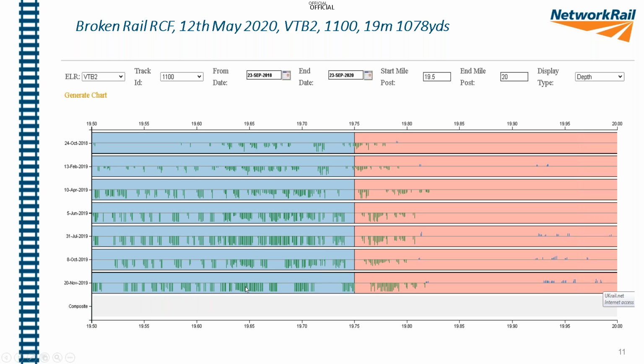But the challenge, I think, with a lot of these is making sure we make best use of all the available information. We tend to look at lots of different things, but in isolation, perhaps not always foreseeing some of these problems. So something perhaps just through the eddy current data we should have seen coming. The RCF was getting worse. It was getting more extensive in the curve and certainly more severe quite quickly. That's a big increase in damage for only a year.